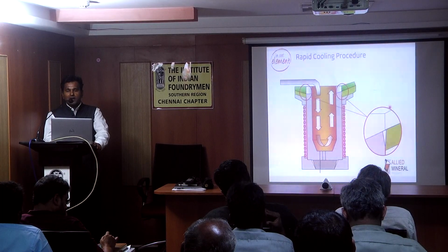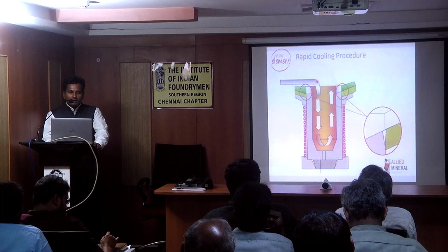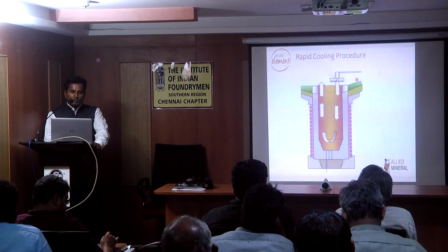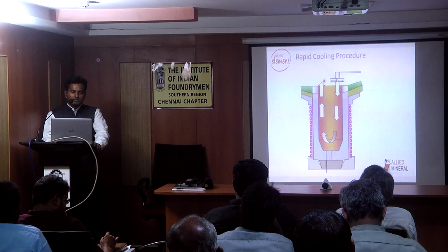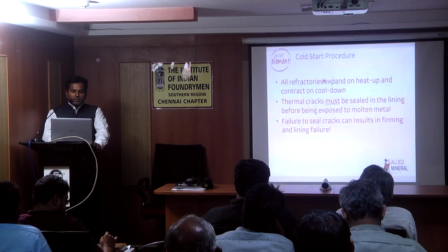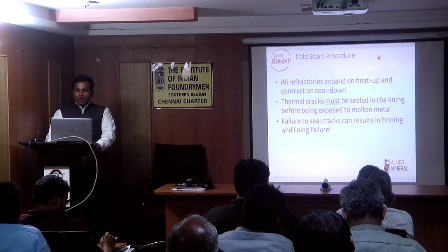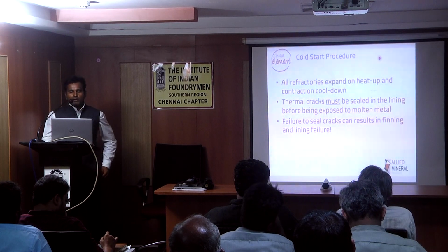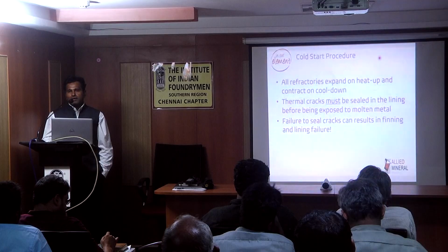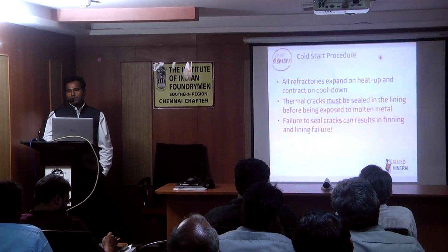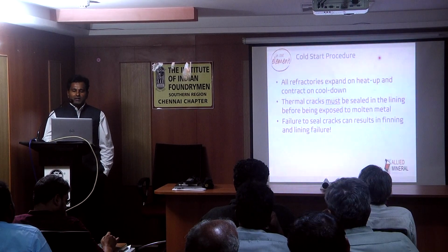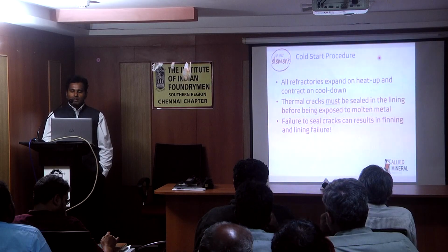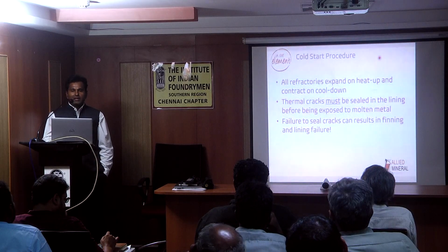So you have to chip off the slag or metal, whatever is present in the joint, and then do the rapid cooling. The other way, you can use a fan for rapid cooling. All refractories expand on heat up and contract on cool down. So these thermal cracks have to be sealed before being exposed to the liquid metal, and failure to seal cracks will result in finning or lining failure.